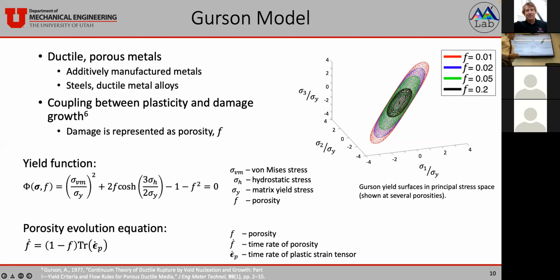What I've shown here on the right is Gurson yield surfaces in principal stress space. I've shown it at several porosities. What I'd like to emphasize here is that we know the von Mises is like a cylinder along the hydrostatic axis. The Gurson model closes that off because it is pressure dependent. You can also see the dependency on the damage variable f. As the porosity increases, the yield surface shrinks, so you see a decreased capability to sustain loading. So the Gurson model is defined by its yield function, which I've shown here. This includes the von Mises stress and hydrostatic stress inside of a hyperbolic cosine term. You can see the dependency on porosity here. It's also defined by the porosity evolution equation, which describes how porosity evolves with loading.